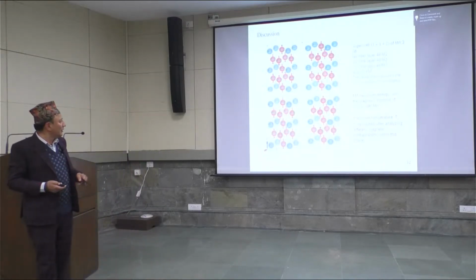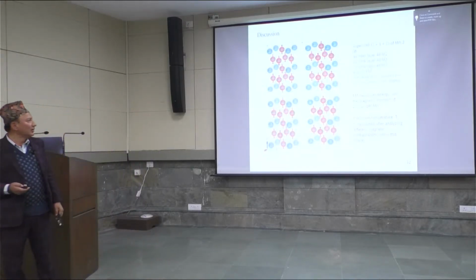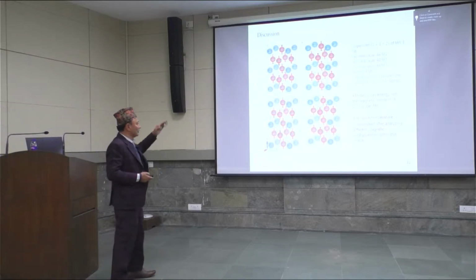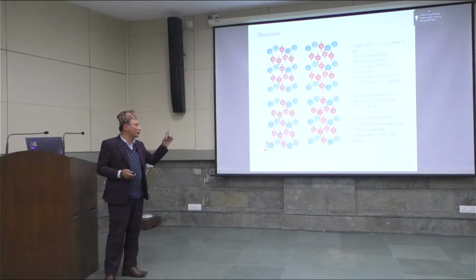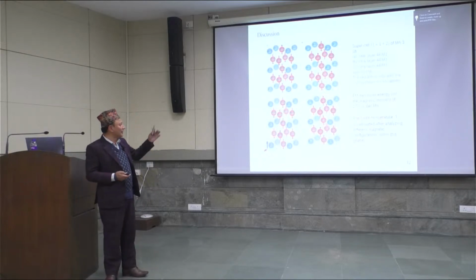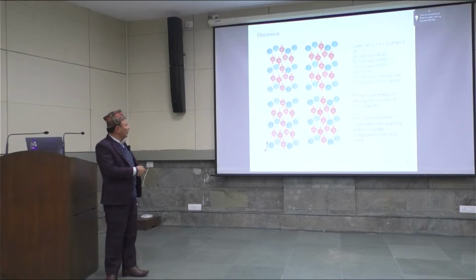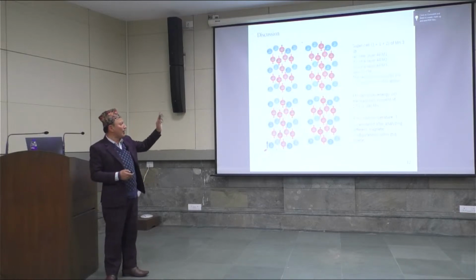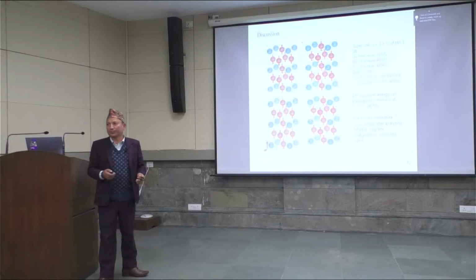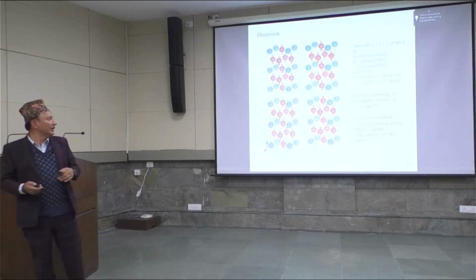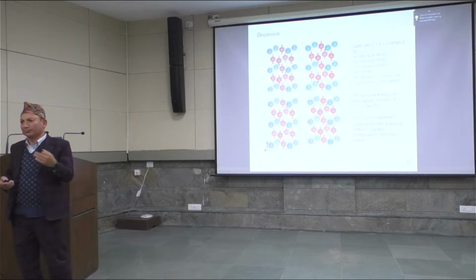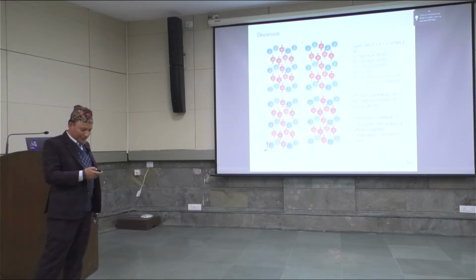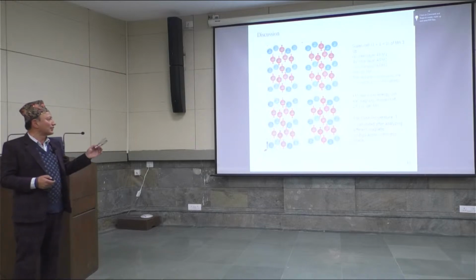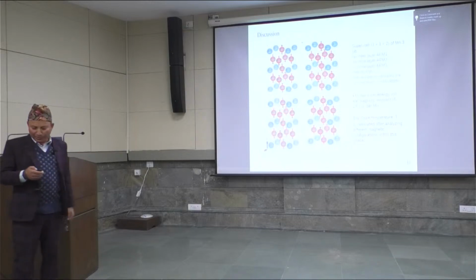Then we went in this direction and made a supercell of 1 by 1 by 2 in the Mn3Sb. We chose antiferromagnetic 1, antiferromagnetic 2, and antiferromagnetic 3, with spin up and down in the interlayer, up-up or up-down. The red arrow indicates spin up and spin down of the Mn atom only, because Mn has d electrons, so it has the magnetic moment, while Sb has no magnetic moment. So we are using only the d atoms, and this also shows ferromagnetic. Ferromagnetic has the lowest energy with a magnetic moment of 2.3 per Mn atom.